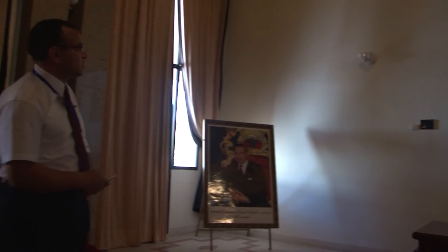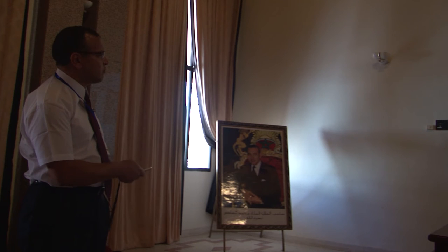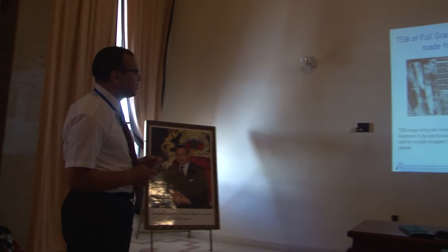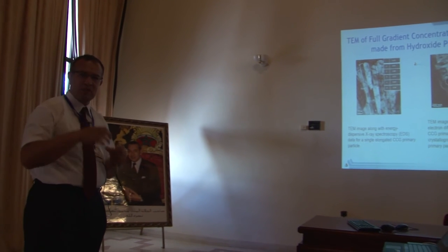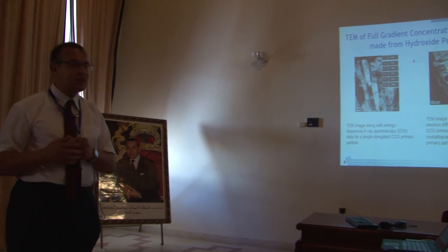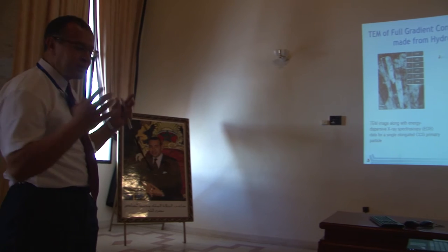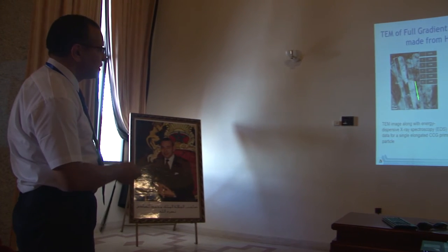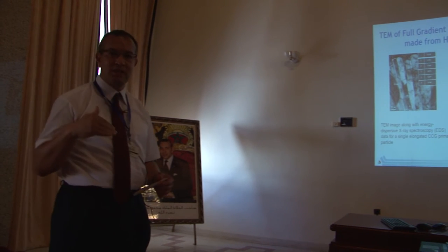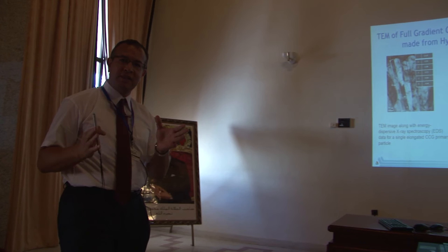If you look a little deeper by high resolution transmission microscopy, we also find, comparing to most of the NMC or NCA, we have actually rods instead of nanoparticles that form a secondary particle. This is a primary particle. So when you do the EDS on this nano rod, you can see that the concentration is changing as well, not only at the secondary particle, but also at the primary particle.